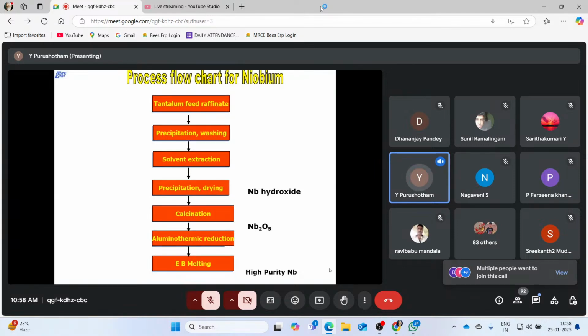And then aluminothermic reduction here, because any metallothermic reduction is required. In the case of tantalum, we used sodium as a reductant. In the case of niobium, it is aluminum. So Nb2O5 plus Al gives Nb and Al2O3. And that niobium thermate has to be purified further by electron beam melting, which is a facility at NFC.